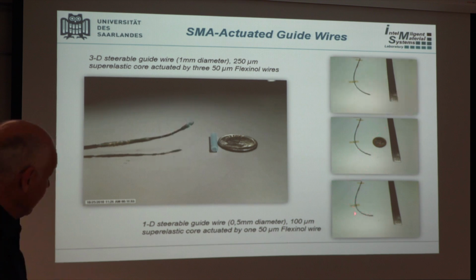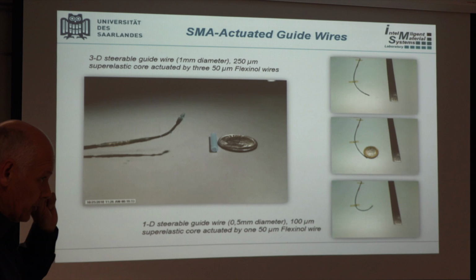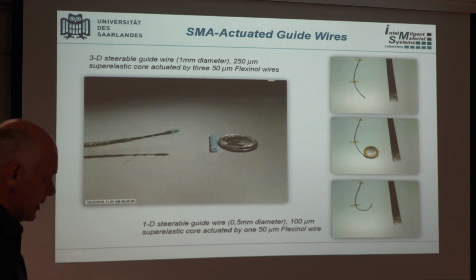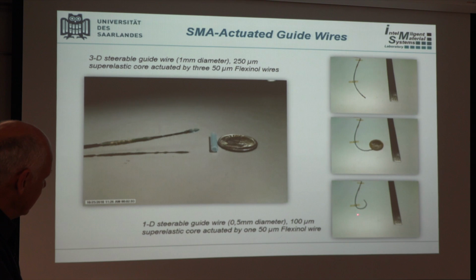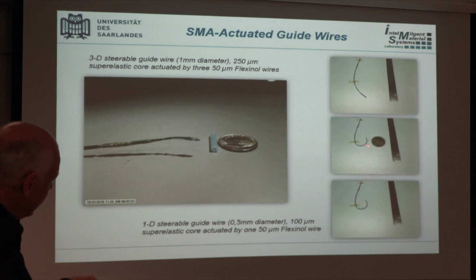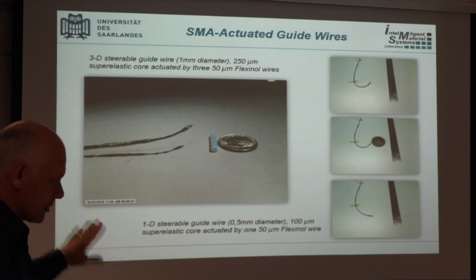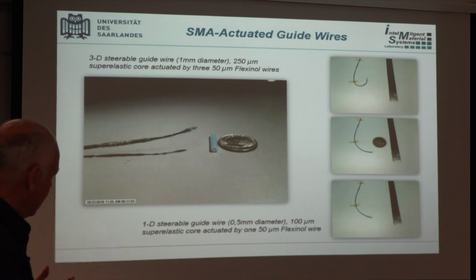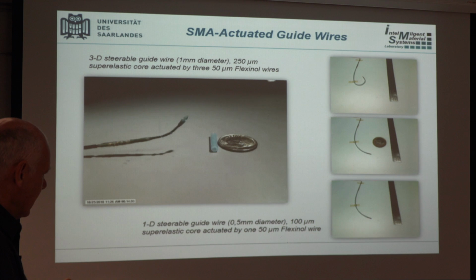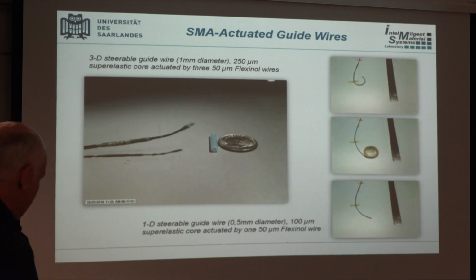You can do it very, very quickly if you actuate it with a strong pulse so that it doesn't heat up over a long period of time. It's covered by a silicone coating, and here you also saw that it's quite strong. It just pushes a coin across the table, and so this is also an application that makes the best of all these properties that we discussed before.